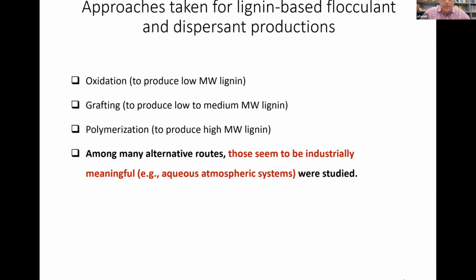Polymerization is another one. Instead of just adding small groups, we can add large monomers and do polymerization and have the chain grow and produce very large molecular weight material, let's say in the order of a million. So I have followed that, but there are many alternative routes available. I just follow those that are industrially meaningful. That means the main focus was on aqueous-based systems, water and atmospheric pressure, no pressurized system.